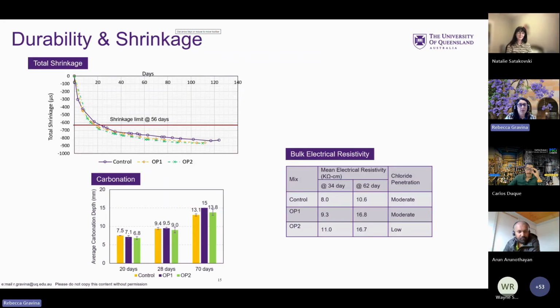the shrinkage performance is a little bit more with the optimised mix designs, as you can see. And also the carbonation, I've shown here some of the carbonation values and the bulk electrical resistivity results. The carbonation was measured up to 70 days, and that's the average depth. It's not all that dissimilar to the control, but there is some variation and difference there that needs to be accounted for.